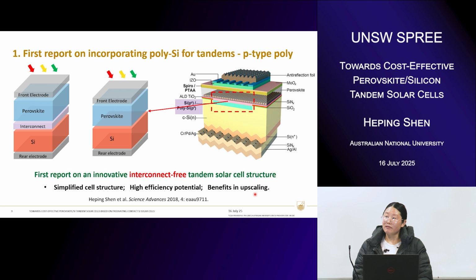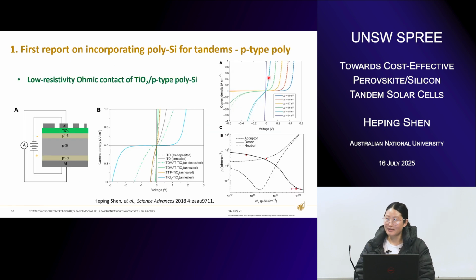And third, it's quite beneficial for upscaling because we deposit this ALD titanium layer on top of the P+, and this ALD layer is quite dense and also not very laterally conductive. So it avoids the potential shunting that could come in from a tunneling junction or the recombination layer, which will become a big problem when upscaling. So it has a few important advantages. We keep on trying to understand how this structure could work, because it's a surprise to us, as usually the titanium oxide and P+ silicon would form a junction having rectifying behavior that shouldn't allow us to have a good ohmic contact in between, which is indeed the case when we use some of the conventional titanium oxide we developed in our lab.